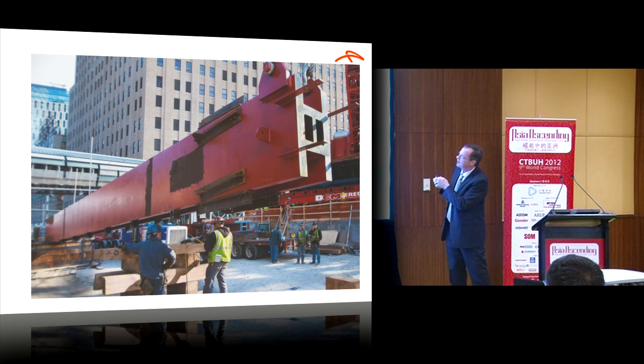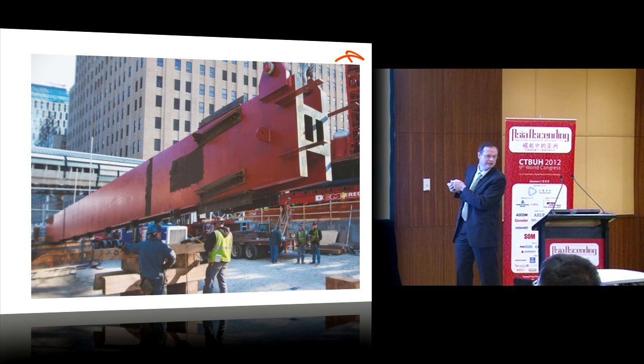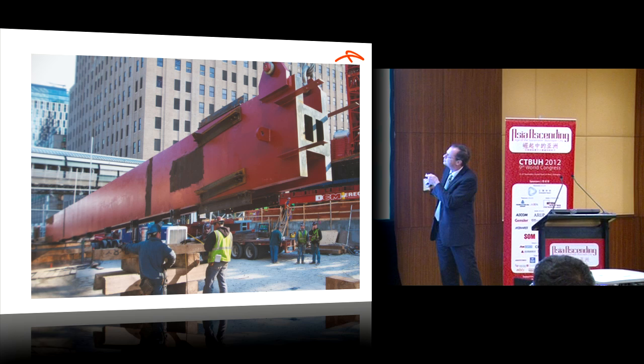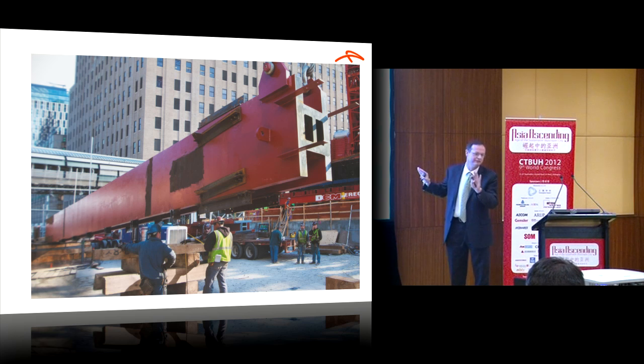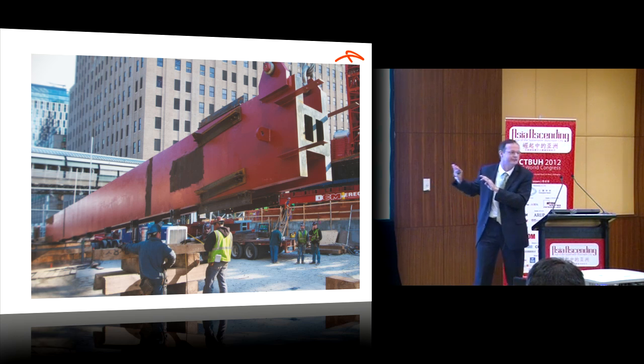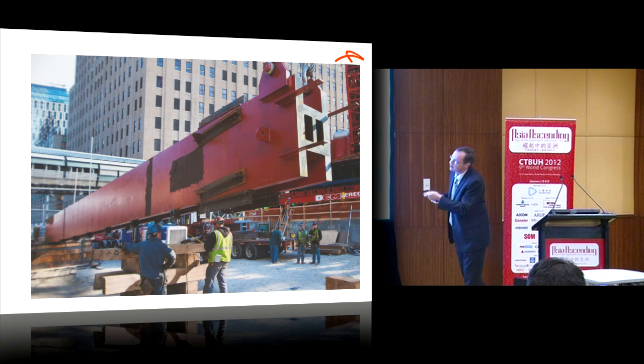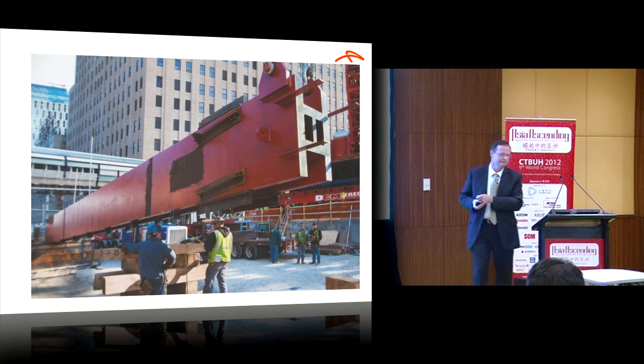And to do the welding here, the port authorities say this doesn't need to be preheated because it's a quench and self-temper material. This needs to be preheated according to the codes to 150 degrees because it's 460 megapascal. So they had to preheat everything at 150 degrees, and the port authorities say you must preheat everything just to be double safe. This building is the safest building on Earth today. And you know how long it took them to do the welding? Seven days, day and night, following the codes.